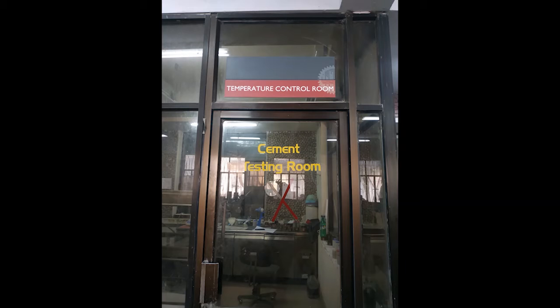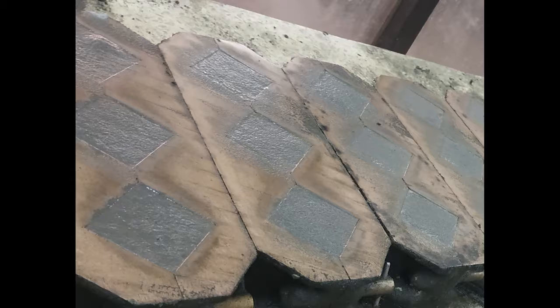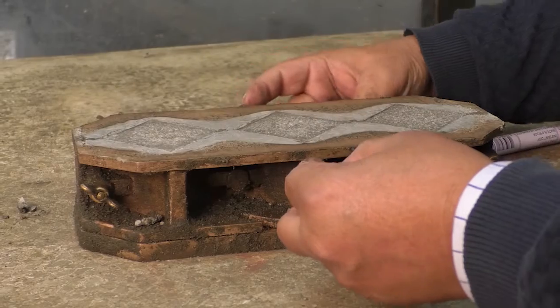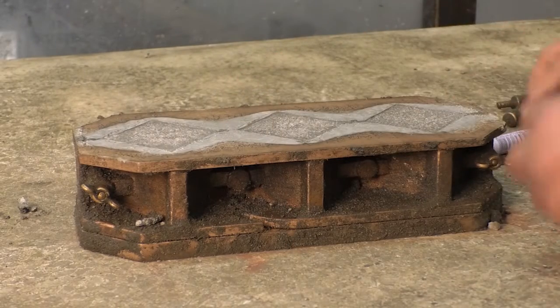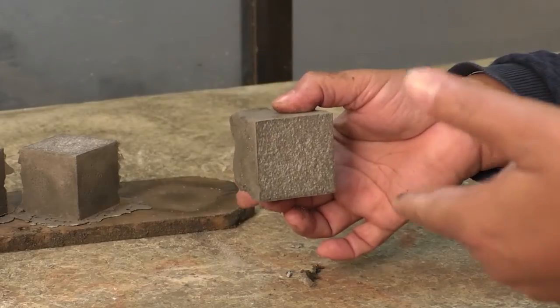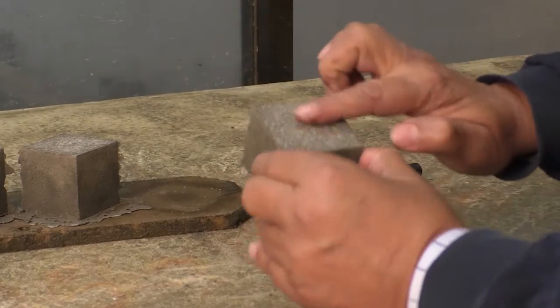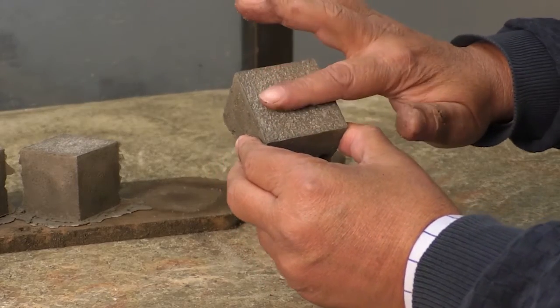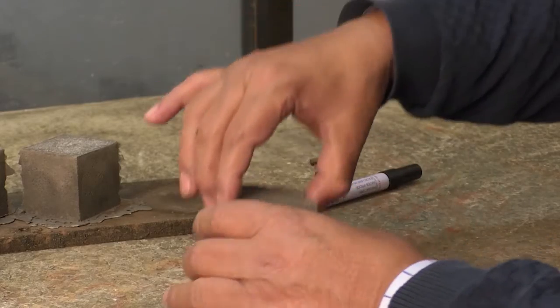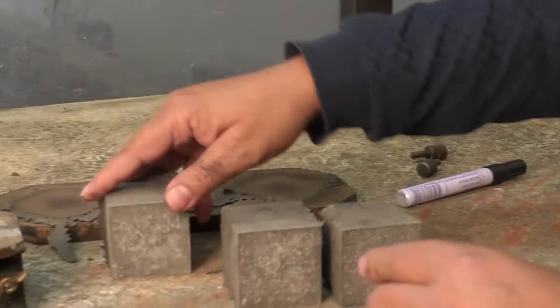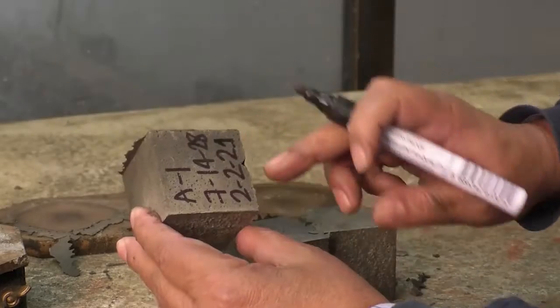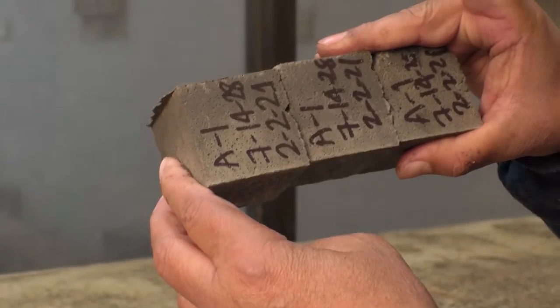Immediately upon completion of molding, we have to place the test specimen in the moist room for 24 hours with their upper surfaces exposed to the moist air but protected from getting wet through water. As you can see from the video, this is how we demold the cube specimens from the mold. Load is applied to the plain surfaces which were in contact with the mold surface, and we have to mark the specimens according to their casting date.